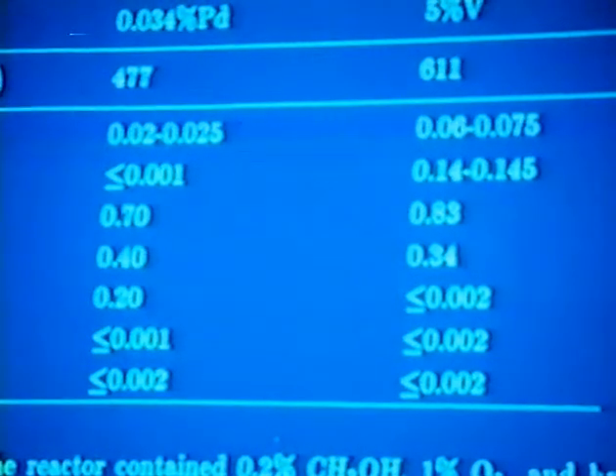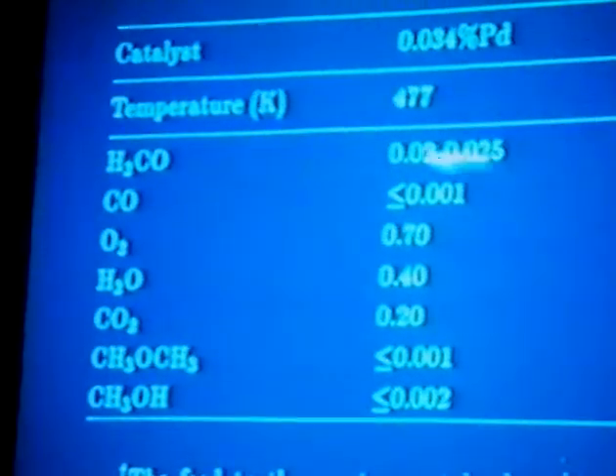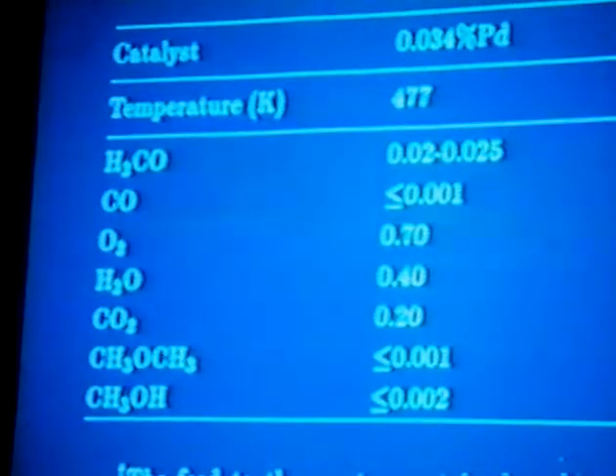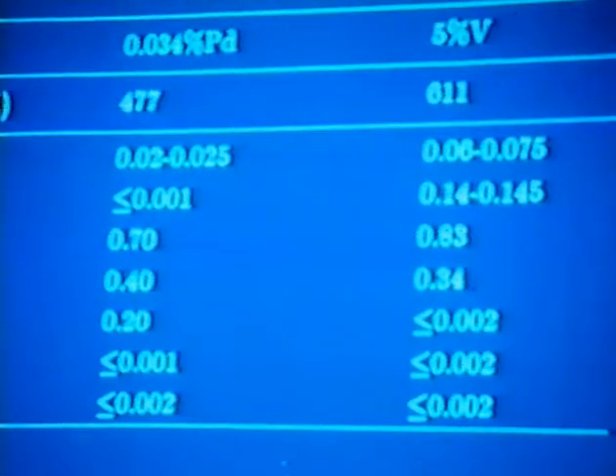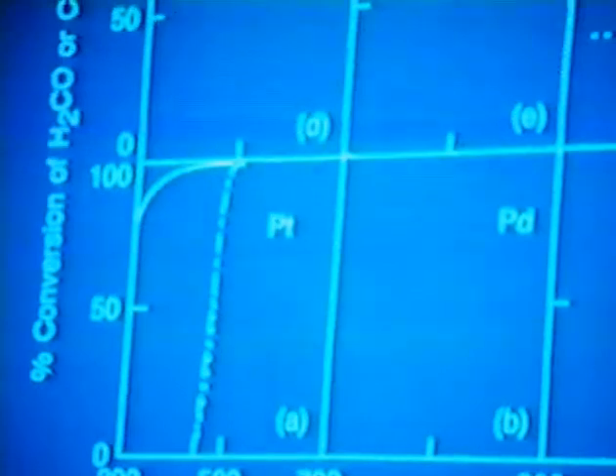So please. And we could generate, starting from about 0.2% methanol, about 0.02 to 0.025% formaldehyde, 200 to 250 parts per million. On the other hand, by using a vanadium catalyst at somewhat higher temperatures, we could get higher concentrations of formaldehyde, 600 to 750 parts per million. But we also inevitably had CO formed as a product. But this is actually not bad, because in a real exhaust stream, you'll always have CO there along with the formaldehyde or whatever organic species you have.